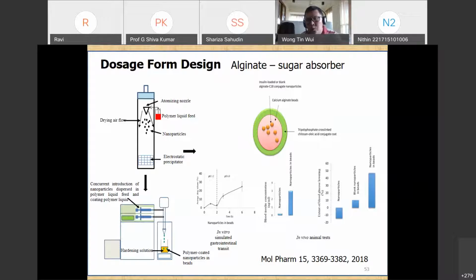Now, in the experiment, we also engage alginate as the encapsulating material for the oral insulin. So we prepare an alginate carbon 18 conjugate to encapsulate our oral insulin. Alginate alone is not used because it can interact with the insulin in an excessive manner, to the extent that the insulin cannot be released and cannot even be detected by the instrument. By designing alginate as an alginate carbon 18 conjugate, it is able to encapsulate the insulin, protect it, yet release it when needed.